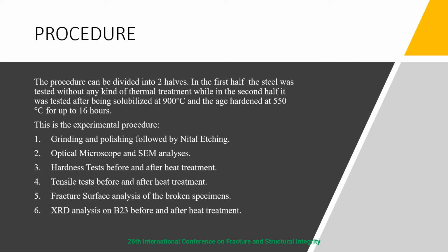The steps for this experimentation can be divided into grinding and polishing, followed by etching with Nital solution for 75 seconds, then optical microscopy and SEM analysis, followed by a hardness test before and after heat treatment. Then a tensile test before and after heat treatment was done. This was followed by a fracture surface analysis of the broken specimens, and finally an XRD analysis on B23 before and after heat treatment.